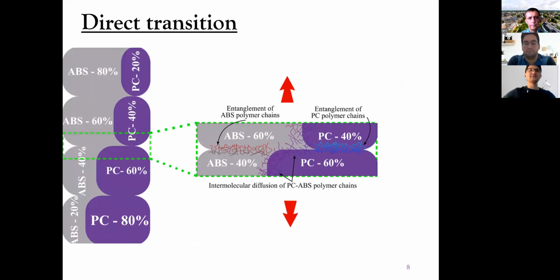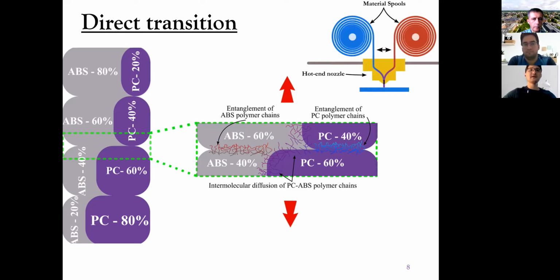So we have ABS, for example, 60% meets with ABS 40%, which have higher entanglement of ABS polymer chains. And for the polycarbonate side, we have more polycarbonate. Polycarbonate to polycarbonate bead to bead adhesion is more than the polycarbonate to ABS interfaces, because we see that in gradient transition, the intermolecular diffusion starts in the mixing chamber, and this is at relatively higher temperatures.